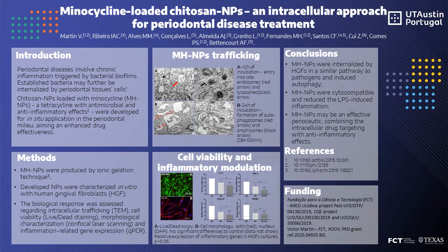Nanoparticles were produced by ionic gelation technique using chitosan solution and TPP. Human gingival fibroblasts were used to analyze nanoparticles' intracellular trafficking, cytocompatibility, and inflammatory modulation.